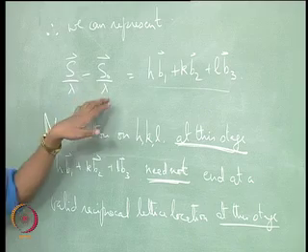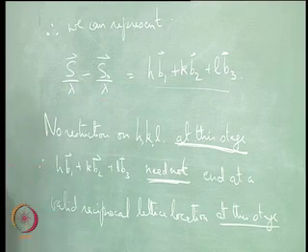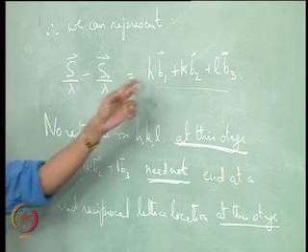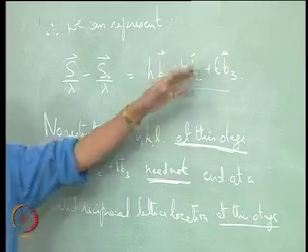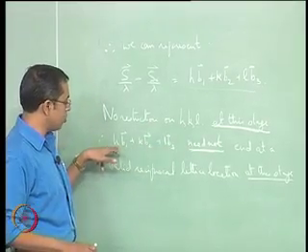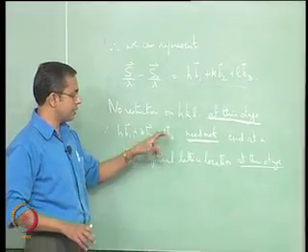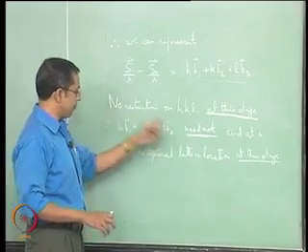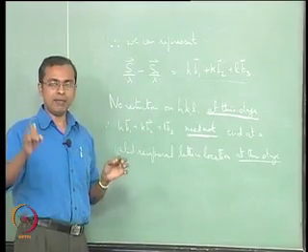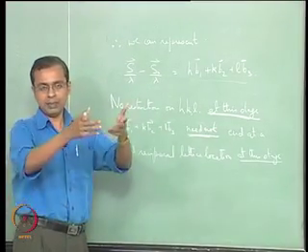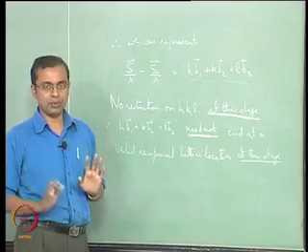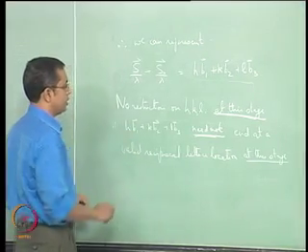So this difference, even though it has all the dimensions of being in reciprocal space and can therefore be written this way, has H, K and L that need not be integers, and therefore this sum, which is now a vector, need not end at a valid reciprocal lattice point. It could end up in some open location where there is no valid reciprocal lattice point. That is the important thing.